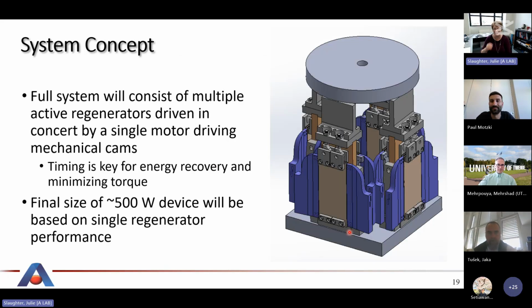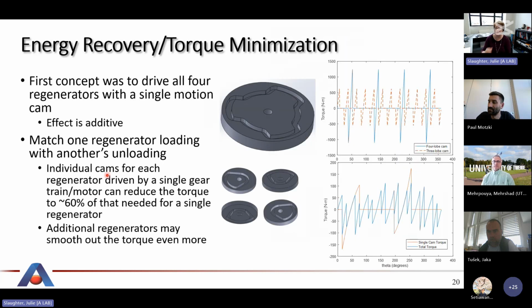But in the meantime, we're looking at that next level. What does the system look like? It's going to have multiples of these regenerators. They're probably not going to look exactly the same, but this is a kind of cartoon. So the final size is 500 watts. If we reach our 125 watt goal, we'll require 4 regenerators. The next thing we looked at is how do we achieve energy recovery with that? Because if you drive all 4 of those at once, you're just going to increase the amount of torque you need by a factor of 4. You can do a little bit better than that if you have, say, a single cam with 3 lobes, you can reduce that by half. But you're still not getting true energy recovery.